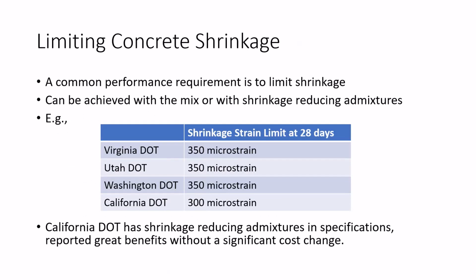The second thing discussed for concrete mix is that limiting concrete shrinkage strain seems to have a big impact. There's really a common performance requirement seen when agencies have these high performance mixes. This can be achieved either with the mix or with shrinkage reducing admixtures. California is a big fan of this, and they reported really great benefits from adding shrinkage reducing admixtures without really seeing an increase in cost all that much.